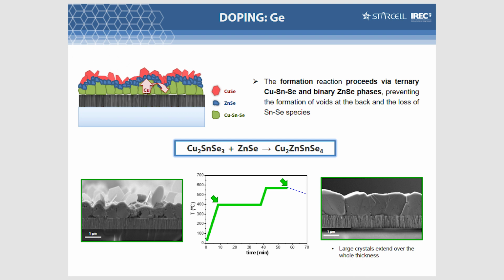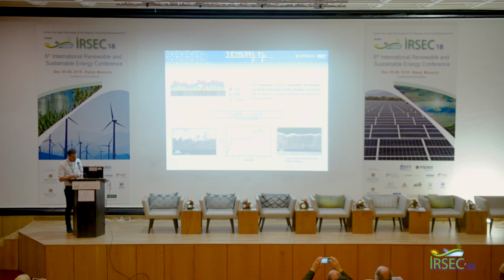This is an advantage because we are not forming any volatile species here. We reduce the tin loss and all the problems associated with this. And also it's a simpler reaction mechanism. You need only 2 molecules to form kesterite, so the probability that the reaction is completed during your synthesis process is much higher. And this is a clear advantage. And in that case, you can obtain even this kind of grain structure, these beautiful, very big grains.